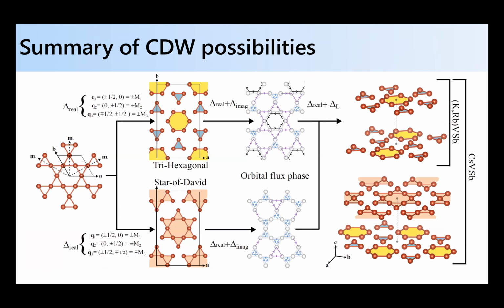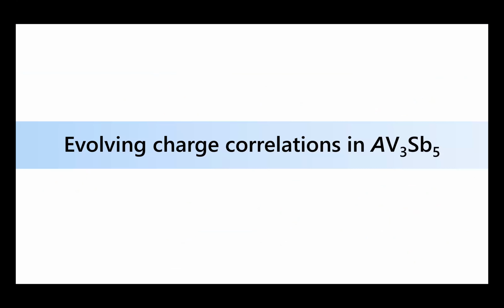Okay, so I'm going to summarize the charge density wave state of these materials and potentially why it's interesting. You start with the kagome net. You have a real component, this 3Q distortion that can either go into a trihexagonal or Star of David state. Each of these can carry a potential imaginary component, which would carry this orbital flux phase, the potential orbital antiferromagnetism that breaks time reversal and maybe drives some of the more anomalous properties. And of course, each of these can have an out-of-plane component, so you can have a staggered trihexagonal modulation in the potassium and rubidium variants, or some larger unit cell that staggers between Star of David and trihexagonal mixed with this staggered trihexagonal state in the cesium compound. All right, that's just capturing what might be going on. Okay, so then we can ask questions.